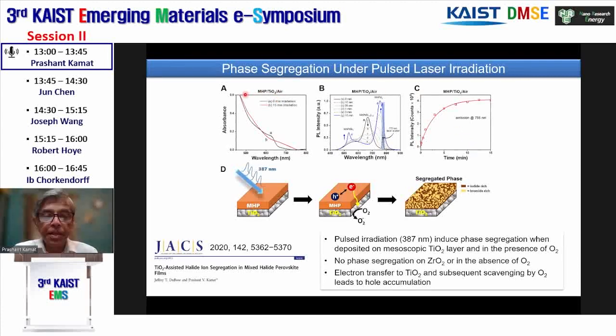Here, this shows you what happens when you have this pulse laser on a methyl ammonium metal halide perovskite. In this case, it is methyl ammonium lead bromide iodide with 50-50 composition deposited on TiO2 and in the presence of air. And what we are seeing here is spectrum A is changing to spectrum B. And you can see it's very similar segregation as you see in the steady state photolysis. You can also follow the emission decay and the iodide emission growth. There is small bromide too in this case we were able to see. And one can follow the emission intensity and get the kinetics.